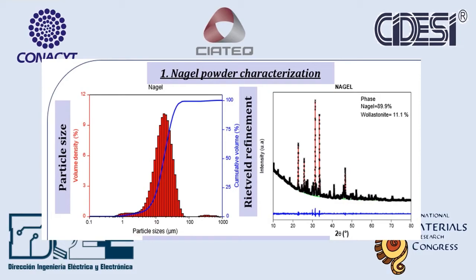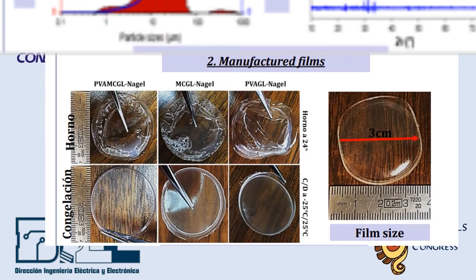Results show that most of the Nagelschmidtite powder particles have a particle size of 18 microns with a distribution from 1 micron to 34 microns. This is a favorable result since particle sizes in polymer matrices are reported to be smaller than 45 microns. The best method for the formation of flat, homogeneous membranes was the physical cross-linking method by freeze-thaw cycles, since the conventional drying method promotes the entry of air into the polymer matrix and leads to rapid solvent elimination, causing defects and malformation in the membranes, which is not desirable for the application as dressing of this type of membranes.